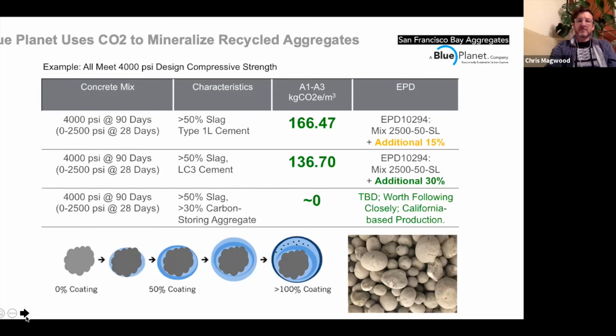I just showed this graph here, this last little row that shows that with about 30% of a carbon storing aggregate replacement of our coarse aggregate, we can get to a carbon neutral concrete. But it's not through Portland cement reduction or injecting CO2, it's actually looking at the aggregate and making an aggregate from the limestone, or making limestone aggregate from waste CO2.